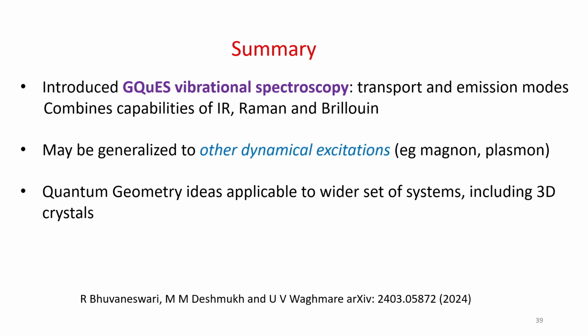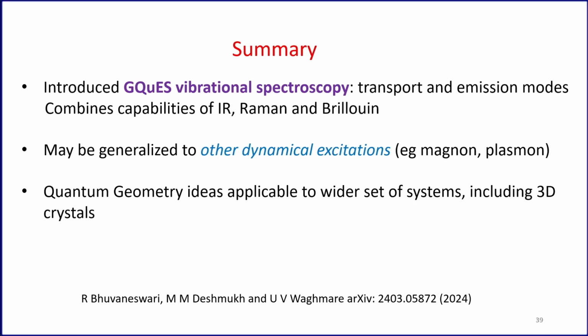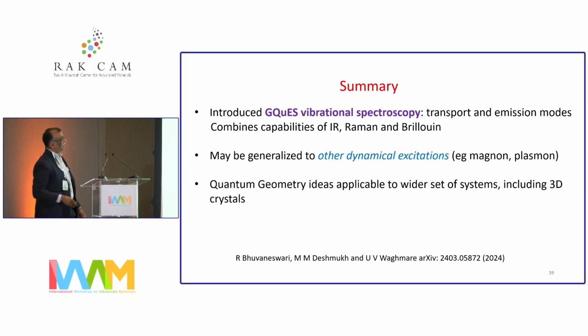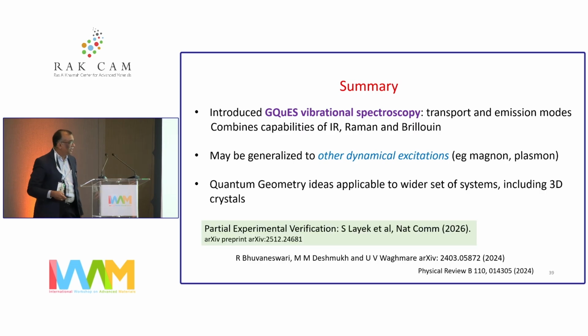I'll summarize my results. We introduced a new experimental technique we call GQuES vibrational spectroscopy in both transport and emission modes, which combines the capabilities of infrared, Raman, and Brillouin spectroscopies. It could be generalized to other dynamical excitations. And the geometry ideas are applicable to a much wider set of systems. It was much easier to show among the wonder materials that Andre talked about, but they will have much richer consequences in 3D. And indeed, we have a partial experimental verification, which is linked to the driven vibration rather than natural vibration of the lattice.